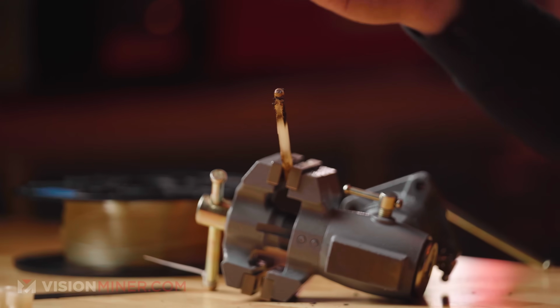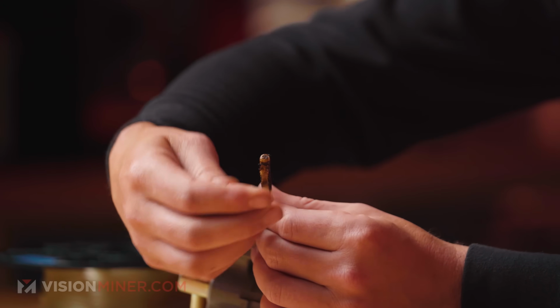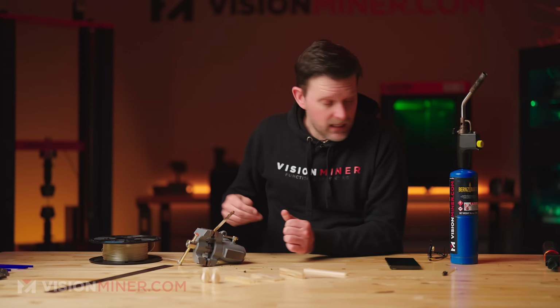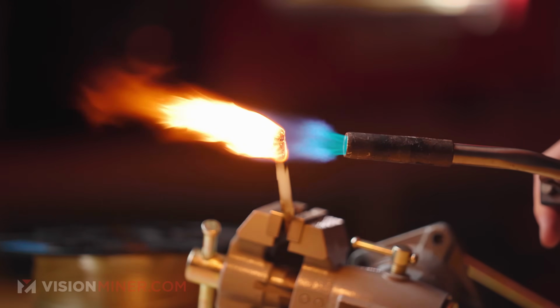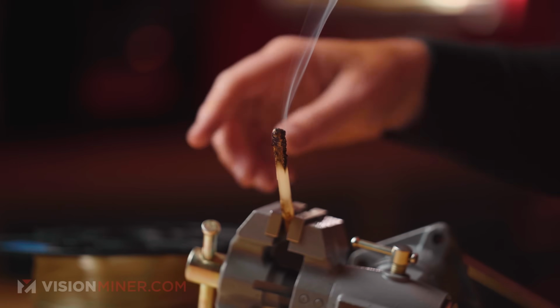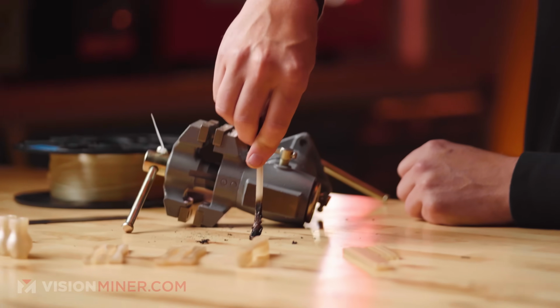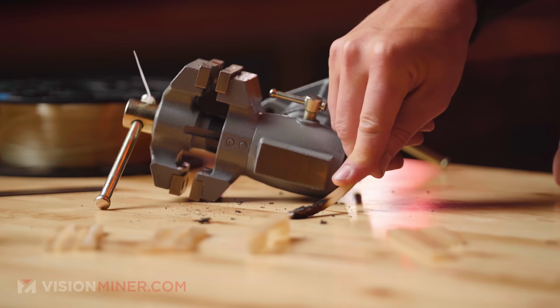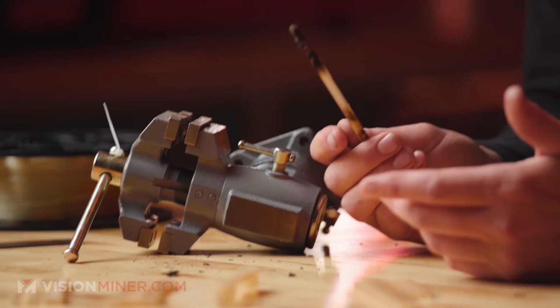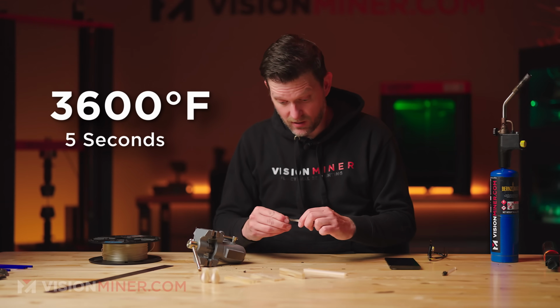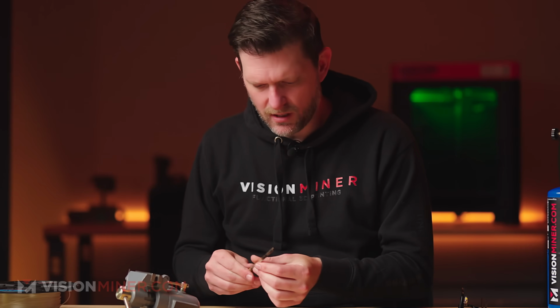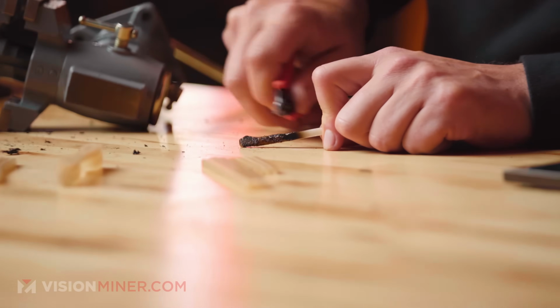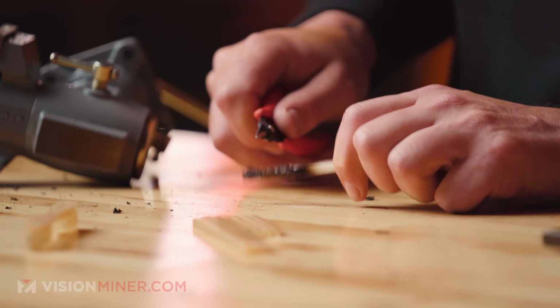So one thing that's interesting about this material is that it doesn't particularly melt cleanly. You're seeing it decompose, and that's where we're getting this residue. But below that residue, there's still a ton of material. And if we actually hit it again, there we go. It takes a lot more pressure, but it's about to be solidified again. And that was exposed to 3,600 degrees Fahrenheit for 5 seconds for a second, maybe third time. Already almost usable again. What's below this? How much material did we lose? We have charring, barely any loss of material.